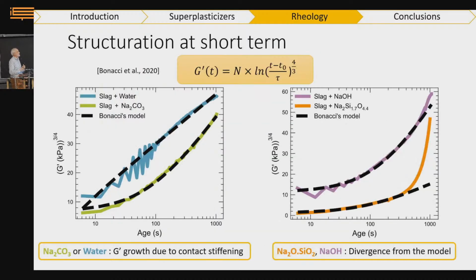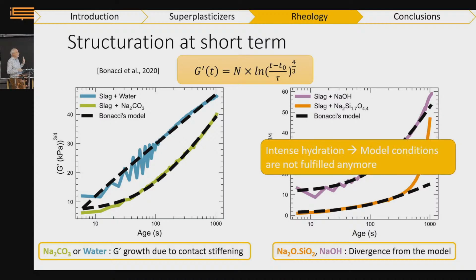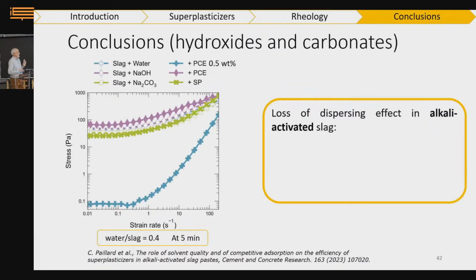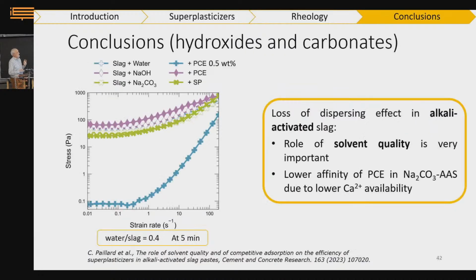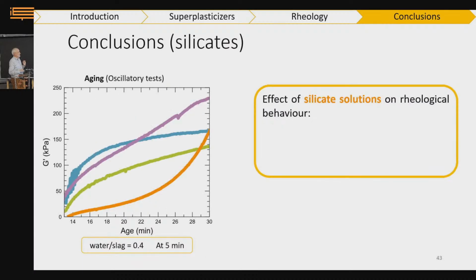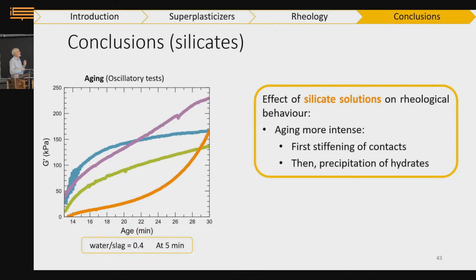So this is to say that here, probably, the growth of the elastic modulus is not associated with contact stiffening, but with a volumetric fraction increase. We are continuously precipitating solids. So again, something very different. To summarize what I said: dispersing effect and solvent quality are very important. Adsorption, of course, also. And in silicates, something is going on that is associated with the initial massive precipitation of solids.